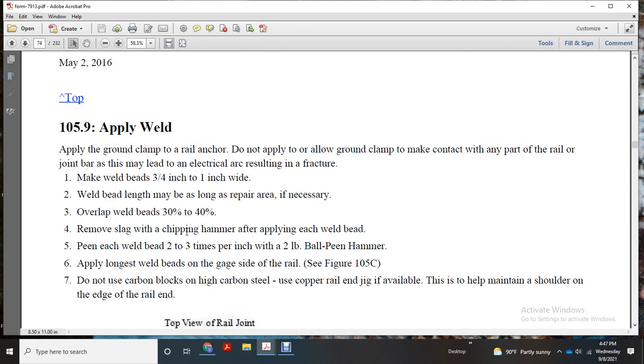Make the weld beads 3/4 inch to 1 inch wide. Weld bead length may be as long as the repair area. If necessary, overlap weld beads 30 to 40%. Remove the slag with a chipping hammer. Peen each weld bead, beating each weld bead 2 to 3 times per inch with a 2-pound ball peen hammer. Apply the longest weld bead on the gauge side of the rail.